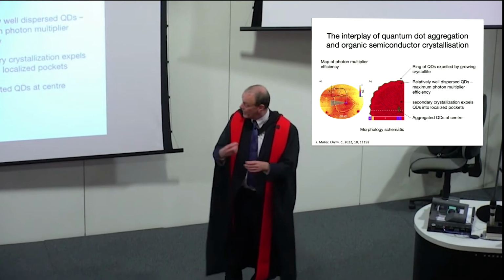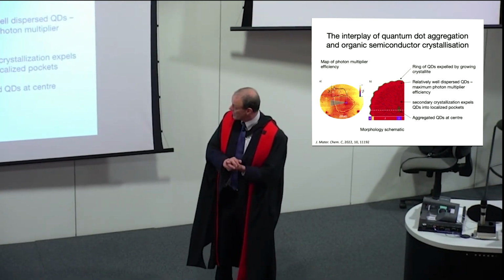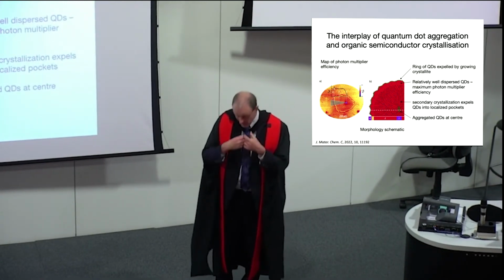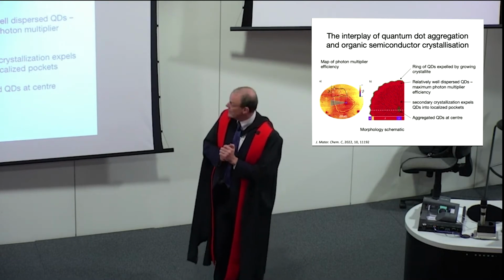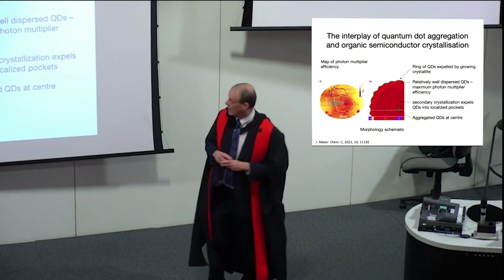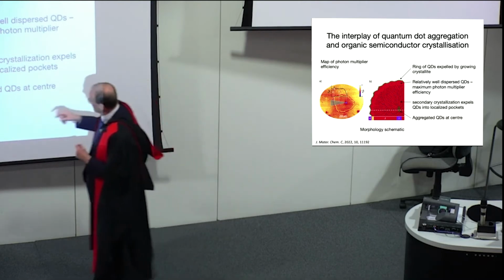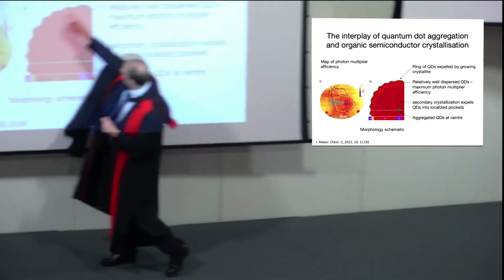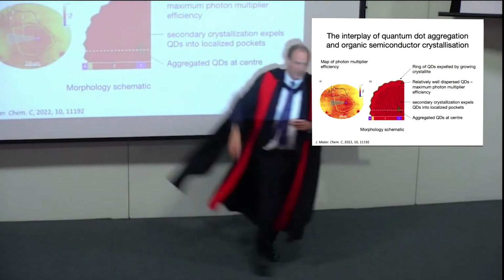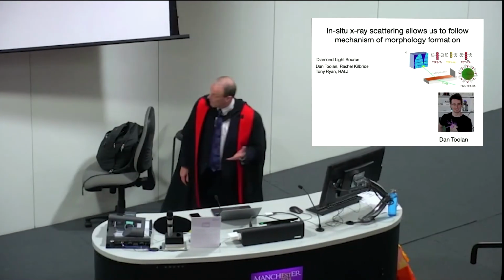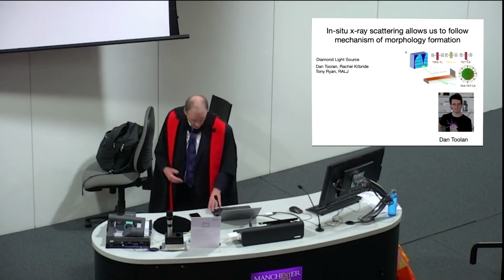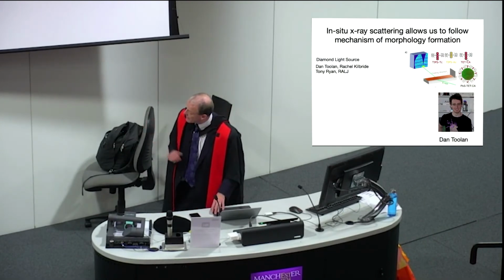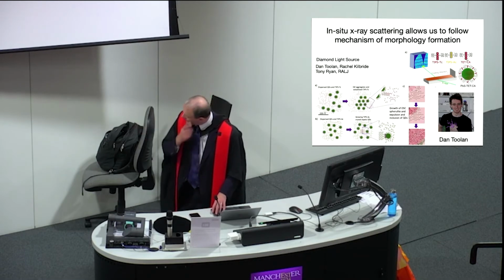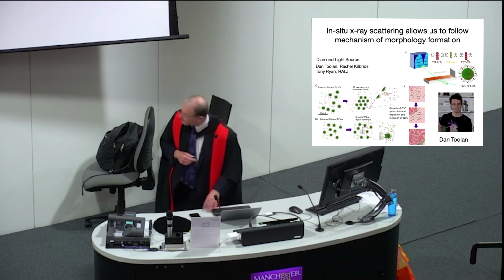Just like zone refining, the organic semiconductor thinks the quantum dots are an impurity, so it just spits them out. And you end up with this very non-uniform distribution of quantum dots where you've got big aggregate in the middle, a kind of coffee ring around the outside, and then better dispersion in the middle. So just to bring this up to date, again, to get a handle on this process and control it, we need to do some kind of in situ X-ray scattering so we can follow the process as it happens. And Dan Toolan, the postdoc, is doing that.